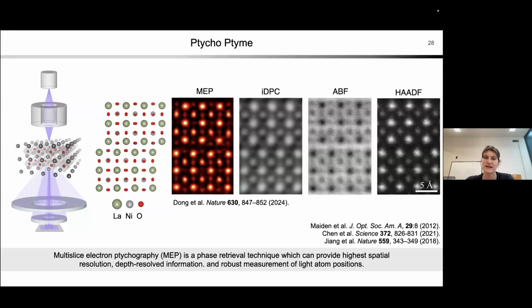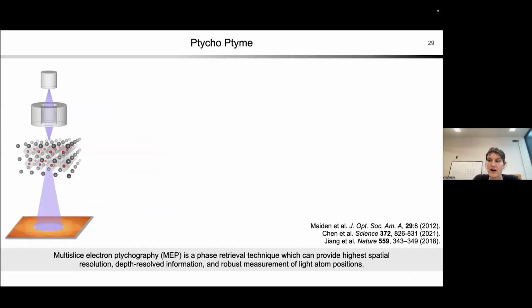So here you see a comparison with some of the other imaging modes. And clearly, the MEP right here in the middle gives us all of those lanthanum nickel columns, but also all of the oxygens that we need. So I don't want to go too much into the details of ptychography. There's many people on the call who know more about it than I do. But the idea is that now by collecting the full diffraction pattern after it passes through the crystal, instead of just using an annular detector, we can do an iterative reconstruction algorithm, right?